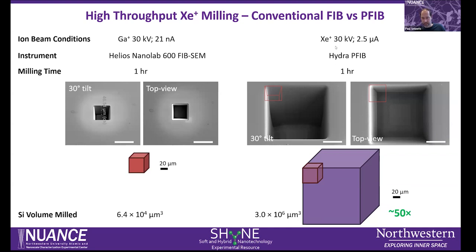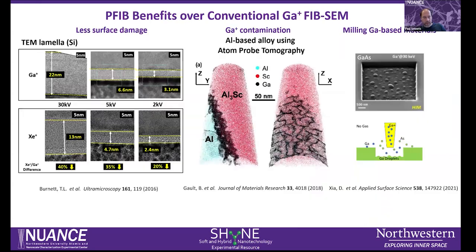In the Hydra with the xenon source, where we can use an ion beam current up to 2.5 microamps, in 1 hour we can remove about 50 times the volume that we can do in the Helios Nanolab.